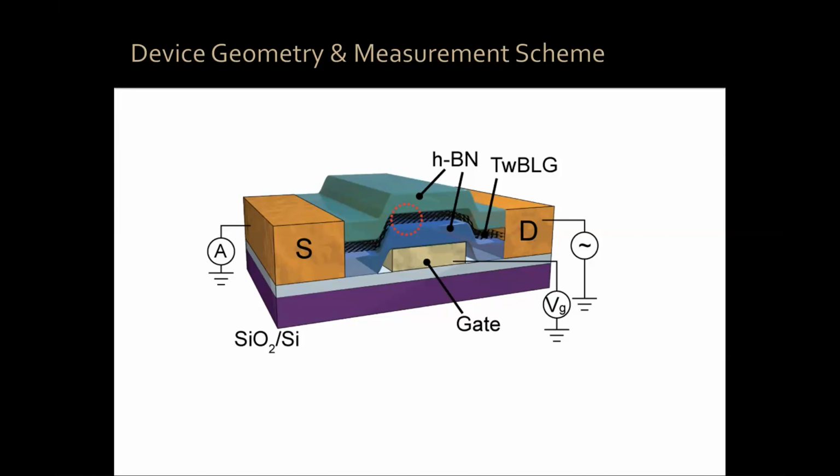And then we have these one or two gates, okay? We have these metallic plates with which they form a parallel plate capacitor with the graphene. Twisted bilayer graphene is one plate of a parallel plate capacitor. This metallic electrode is another plate of the parallel plate capacitor. So I apply a gate voltage, and I can vary the charge density in the plates of the parallel plate capacitor. That's how we vary the charge density in the twisted bilayer graphene, okay?